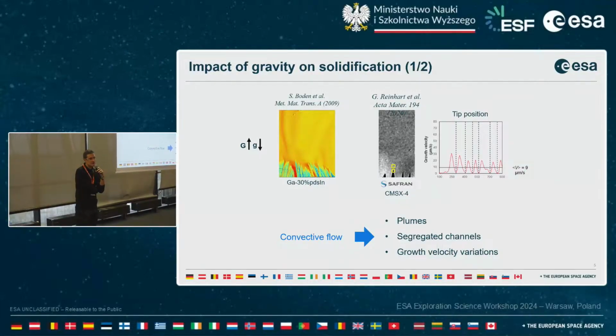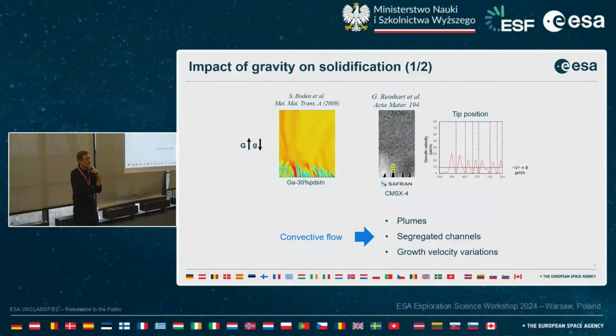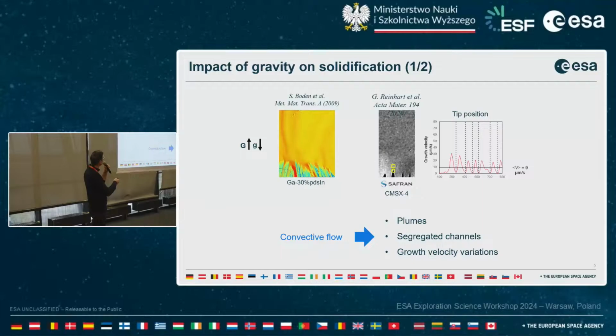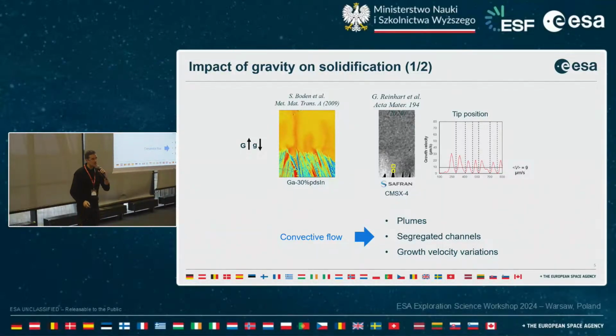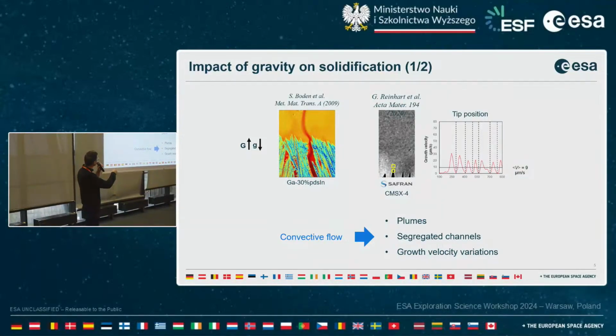So here are a few illustrations of these gravity effects. First one will be the impact of convective flow. You can see here a picture recorded during the directional solidification of a gallium-indium alloy. When you solidify, you reject gallium that is light, and this light solute in the liquid will tend to go up and create these nice so-called solute plumes that will interact with the solid. You can see that it disturbs a lot the development of the microstructure and can even create liquid channels inside the mushy zone, the partly solid, partly liquid zone. So it has a major impact on the development of the microstructure.